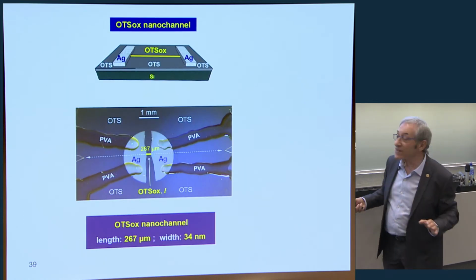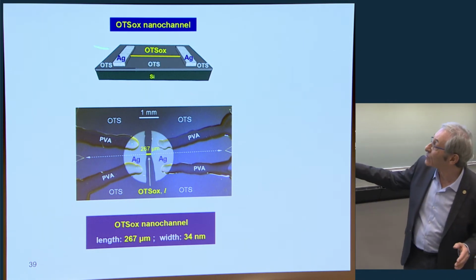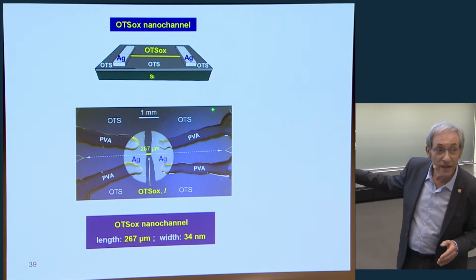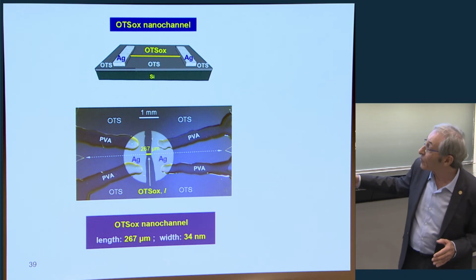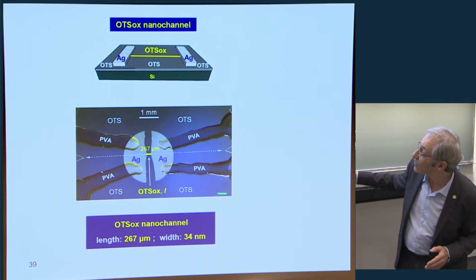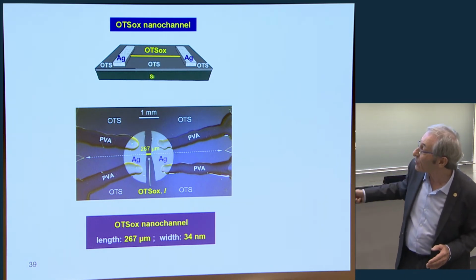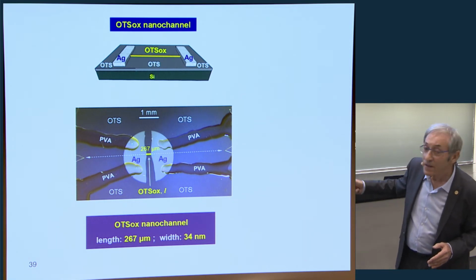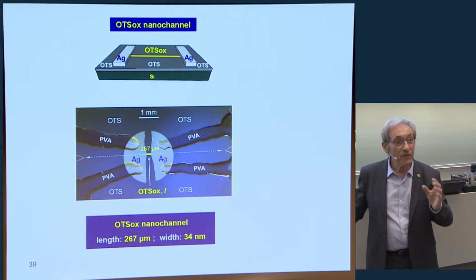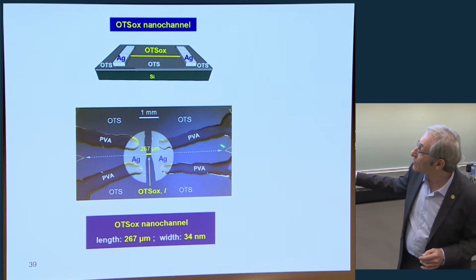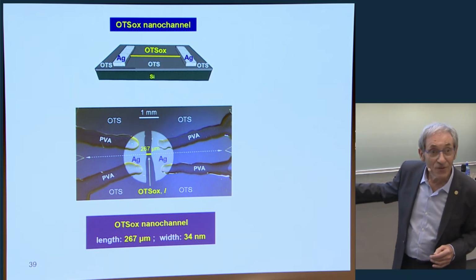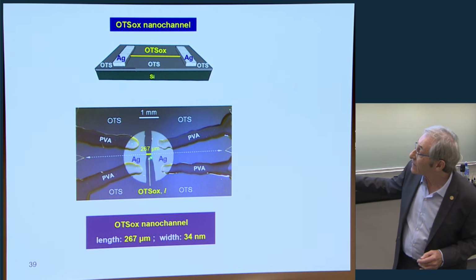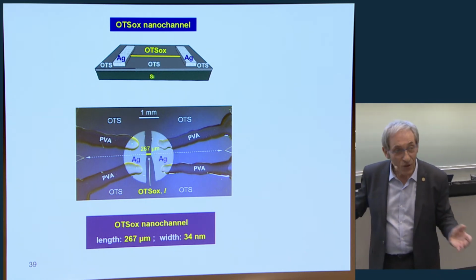Now, this is how such a device looks. I mean, this is the cartoon, and this is an optical image taken from the top. This is a piece of silicon wafer coated with the OTS monolayer. The line is written with the electron beam along this line between two scratches, okay? What you see here in yellow is just to show where it is.